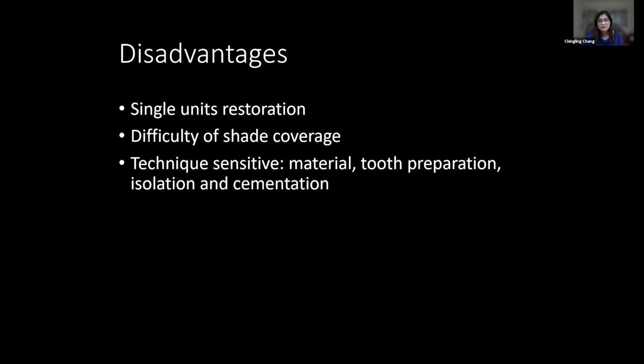But some disadvantages are that most of this kind of restoration is good only for single units. It's very difficult to do a bridge with this kind of restoration. And for some teeth with very bad discoloration, maybe from caries or from root canal treatment, it's very hard to cover the shade with the porcelain restoration and achieve a good result, because it has very good translucency. So you can't really get a good result by just putting in a clear translucent porcelain restoration. Also, it's very technique sensitive because we use a lot of different materials and we have to deal with that.